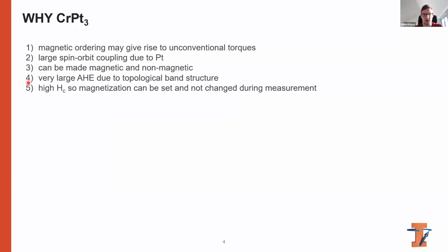Fourth, it has a very large anomalous Hall effect due to its topological band structure. Finally, it has a high coercive field, so the magnetization can be set with a large magnetic field and then not changed during the measurement. So we can take a look at the spin torques generated with different coercive field saturations.